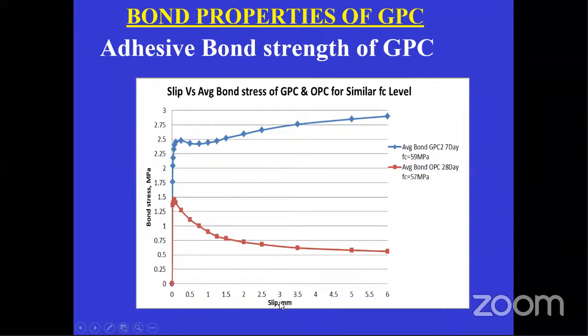This is the bond strength study. This was done by my PhD scholar, Mr. Bhupalan, who proved why the bond strength of geopolymer concrete is better than ordinary concrete. I wanted to prove it, so we studied the chemical adhesion separately, and he proved it, bond strength versus slip, having this condition. It was the most common. Even in reinforced concrete, fiber reinforced concrete also, you'll get this curve only. But in geopolymer concrete, we can see a strain hardening type. That means the bond is always slowly increasing, not suddenly like this. So this gives us a better structural property. I just wanted to tell you.